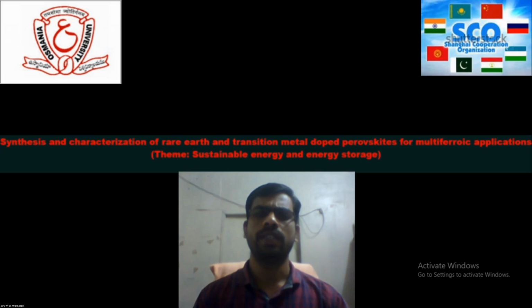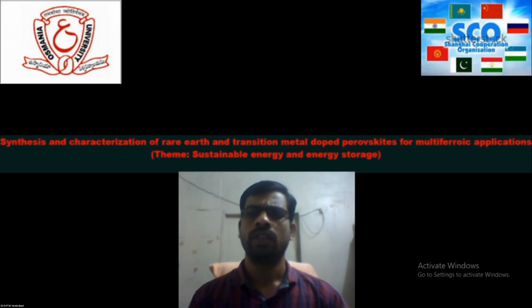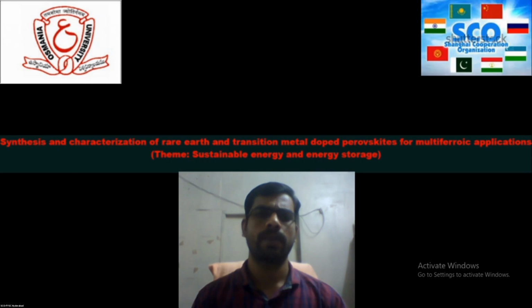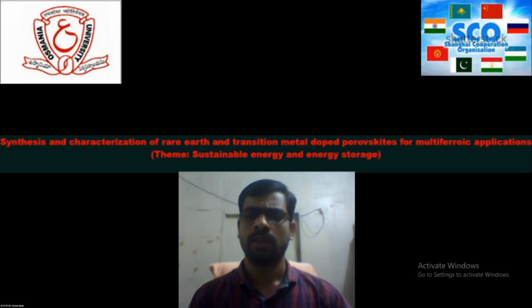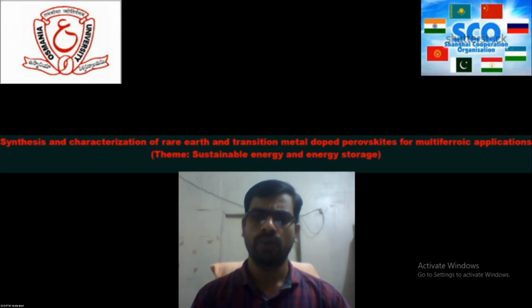M-T plots of NdCr1-xFexO3 perovskite system were carried out up to 300 Kelvin at 0.01 Tesla and 0.5 Tesla fields. M-T curve of x equals 0 and x equals 0.3 samples at 0.01 Tesla field exhibited novel magnetic diamagnetic-like behavior. With further increase in temperature and Fe content, reversal magnetization disappeared. NdCrO3 perovskite showed relaxor ferroelectric behavior between 178 degrees centigrade at 100 Hz to 225 degrees centigrade at 1 MHz. These materials are useful for capacitor, superconductor, multiferroic, and energy storage device applications.